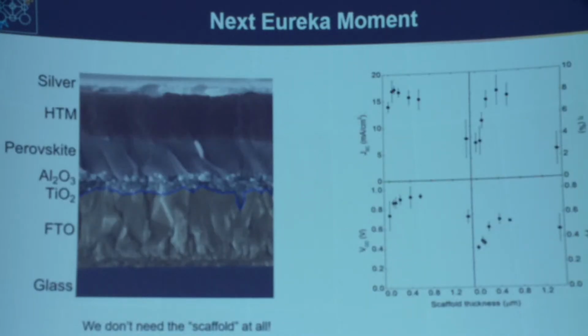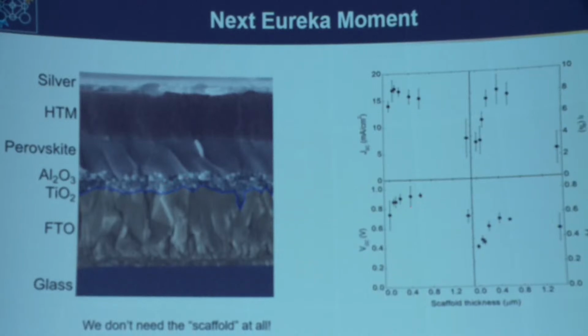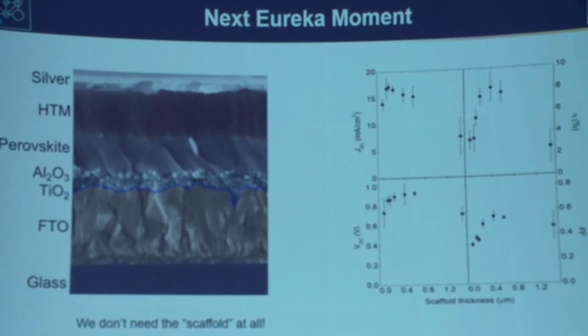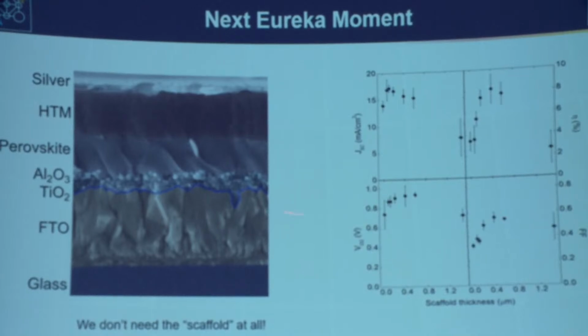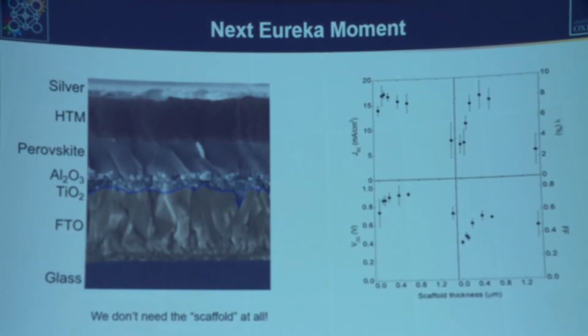The next Eureka moment, which is sort of a logical progression really: when we were optimizing these devices, we had this porous alumina as our scaffold. We found that the devices got better and better as we made this alumina thinner and thinner, to the point that we couldn't believe the perovskite was really going into this 50 nanometer thin porous alumina.